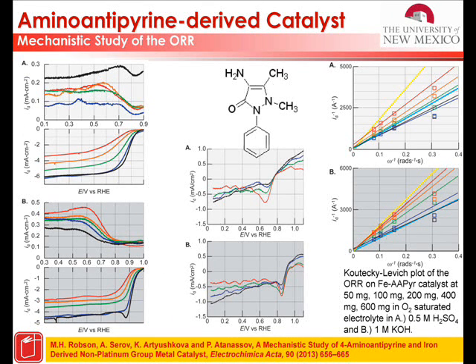And you yield a very active catalyst. Of course, we support that on silica. Then we remove the silica away. You get this open frame structure. There are particles of iron, because there was an iron nitrate in part of the salt, and those particles of iron are covered by the graphite-like structure. Now, the majority of the oxide is removed because of the etching we do with HF. And HF removes all the oxides and all exposed iron. So only the iron that is fully encapsulated like this particle will remain. And still it makes about 1.5% by weight.